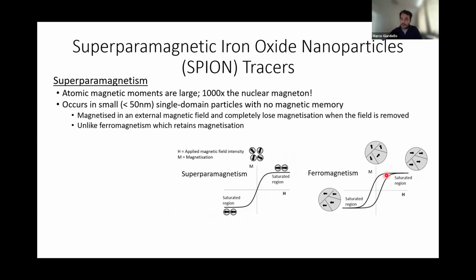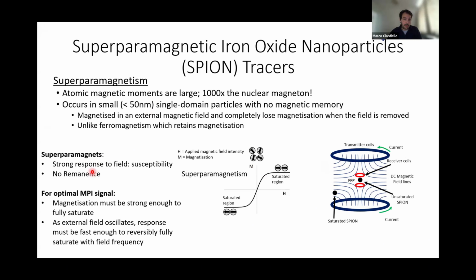In ferromagnetism, it will retain some of that magnetic behavior. Instead of immediately demagnetizing, like a fridge magnet, for example, it maintains its magnetic property. You have to pull the magnetization away, which is why you get this curve that looks like this in one of these hysteresis loops. Why that matters: superparamagnets are very strong, they're very high like this. But why that matters is, in principle, what you would want is in that field-free point. The way I think of it is you're oscillating this field.